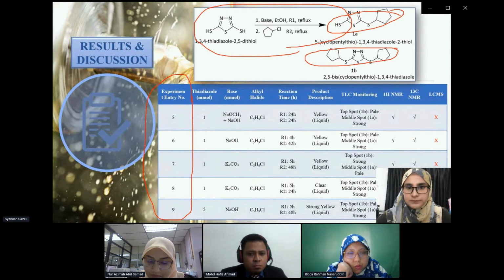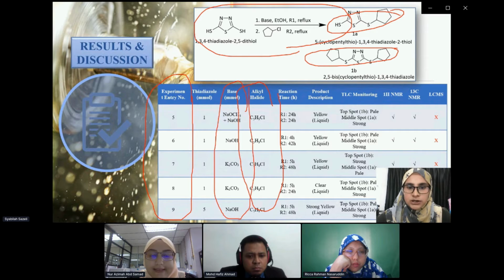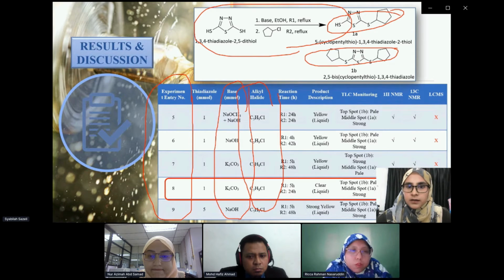for the product purification. For the alkyl halide, this time we are using chlorocyclopentane, while for the bases, we use different types of bases such as sodium methoxide, sodium hydroxide, and potassium carbonate to promote the green technology of producing monoalkylated and bisalkylated 1,3,4-thiadiazole. So from our analysis, it shows that entry 8 is suitable to use as the optimization condition because of the low toxicity of potassium carbonate and also it is lower in price than the other 2 bases.